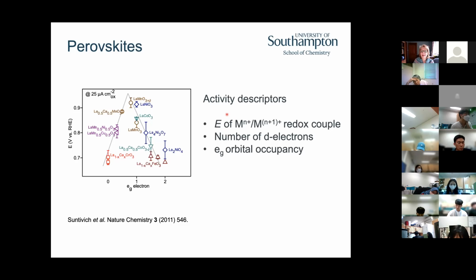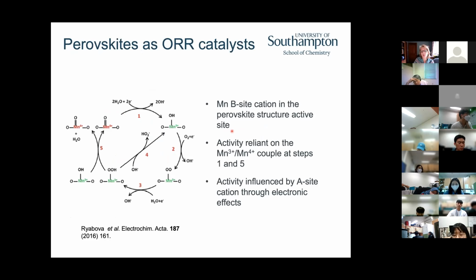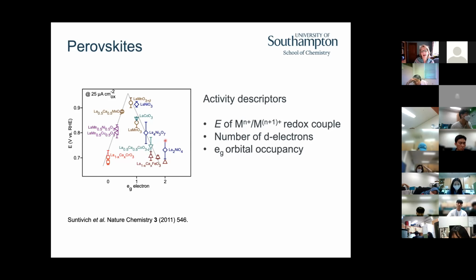And why is this one the best? Well, there's various activity descriptors in the literature. It has to do with the redox couple, right? What potential can you go between these two? It has to do with the number of d electrons and the EG orbital occupancy. In this case, we have a partial occupancy of that EG orbital. So there's only 1 electron in it, and that seems to give us the best descriptor in the literature.